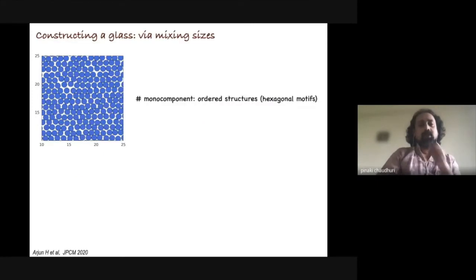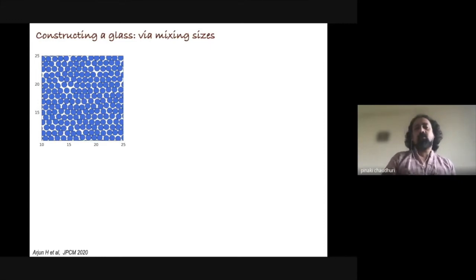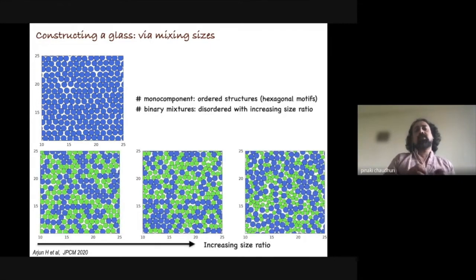So for example, if you have a one component system where you have a collection of disks, let's say hard disks, at very high density, this has some kind of order, which is you have these hexagonal motifs that are forming inside the system, and you have a repetition of these hexagonal motifs across the space. Now, if you start having mixtures of these particles of two different sizes, these hexagonal motifs start breaking apart as you go on increasing the size ratio.